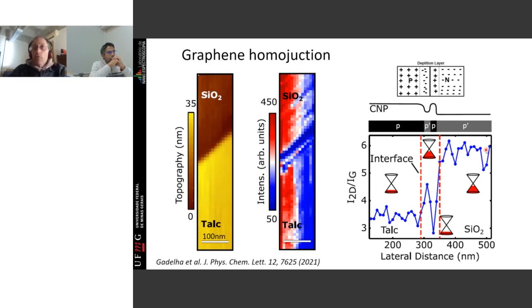This is very interesting because what you are measuring here is doping, so the material is heavily doped here and lightly doped here. And at the interface, you have an oscillation because, here is a PN junction, okay, which is the most common. Every time you have a junction, you have in the middle a depletion layer. And when you control this depletion layer, this is what you do when you have to control a transistor, like the 0, 1 in a computer, meaning having current going through or not having current going through.